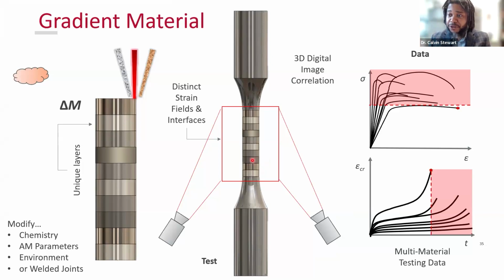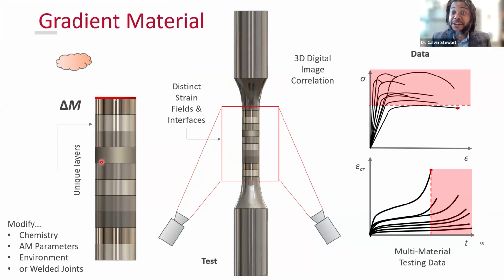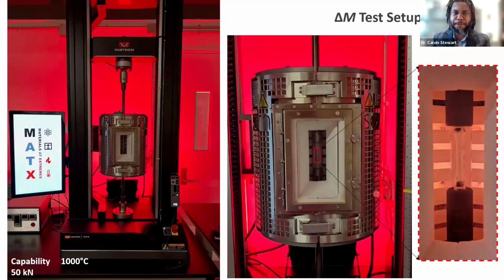If we do that, if we're able to create components with these unique layers with different chemistry, then we can create one sample that, say, represents 10 or 20 different chemistries that we think might be good candidates, and then run this correlation to determine, of those 20 chemistries, which one do we want to build those full bars of? Which ones actually have the empirical evidence of goodness? Our computational models tell us that they should be good, but which one actually empirically, or which range of chemistry is the sweet spot that we should explore, right?